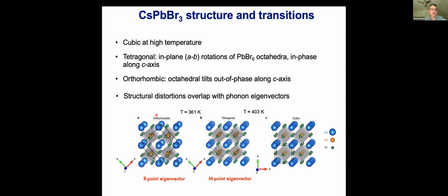What's very important, and perhaps the main message of this study, as I'll show you, is that these crystal structures shown here are really just time and space average crystal structures. There are very large fluctuations that actually modulate this average crystal structure and are indeed related to the phonon dynamics and are important to understand the electron phonon coupling. But if we stick to this simple sequence of crystal structures here, these, as in all the oxide perovskites, are understood in terms of phonon eigenvectors of the high symmetry parent structure. So for example, the M-point phonon for this tetragonal distortion and R-point phonons for further orthorhombic distortion, okay?